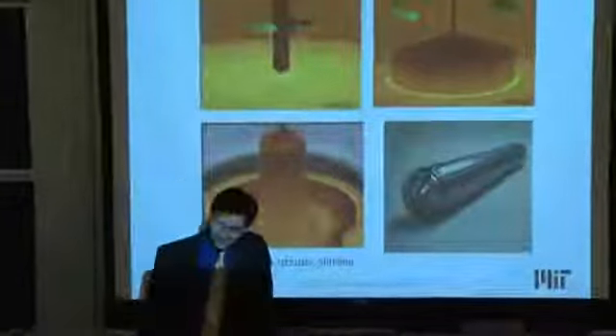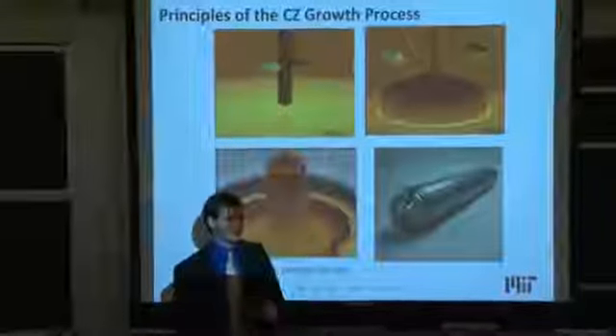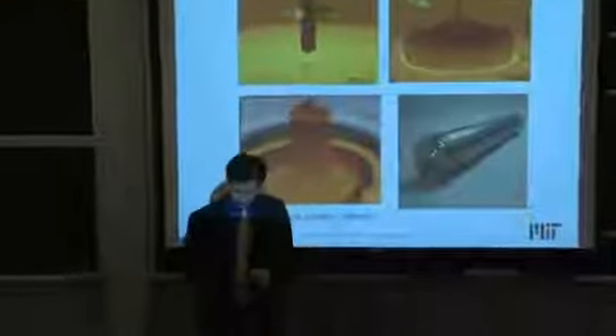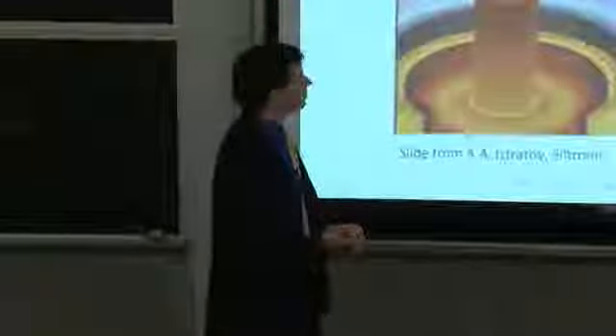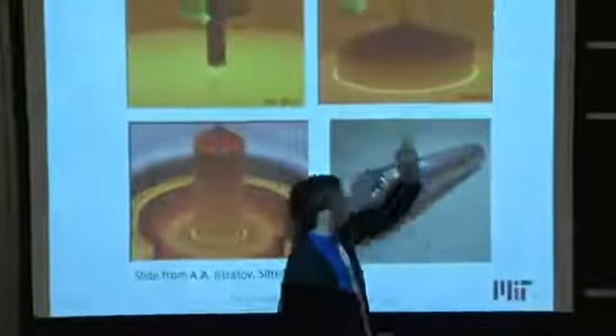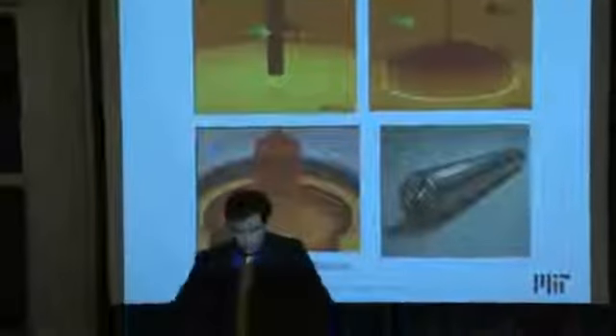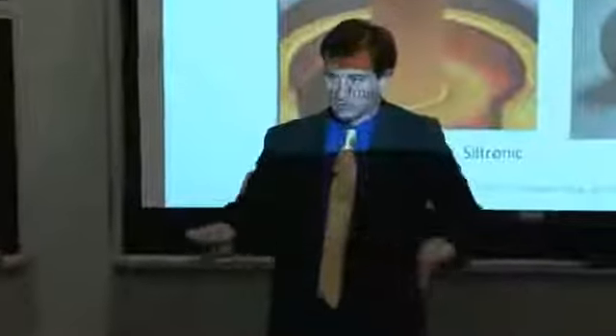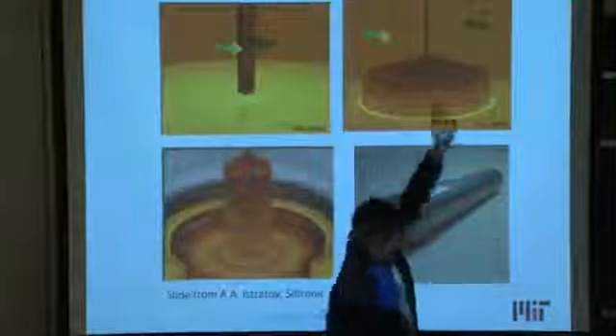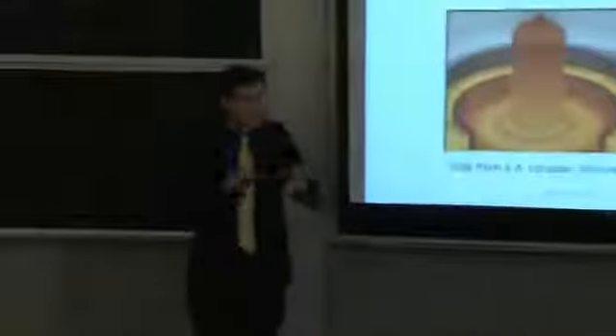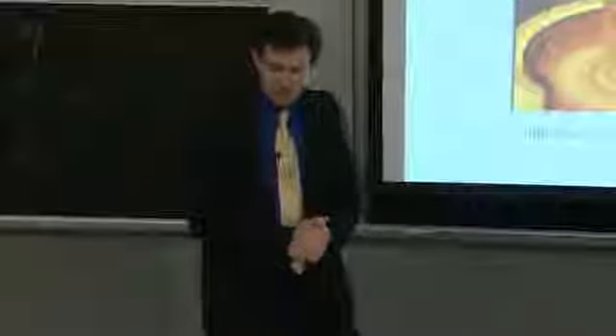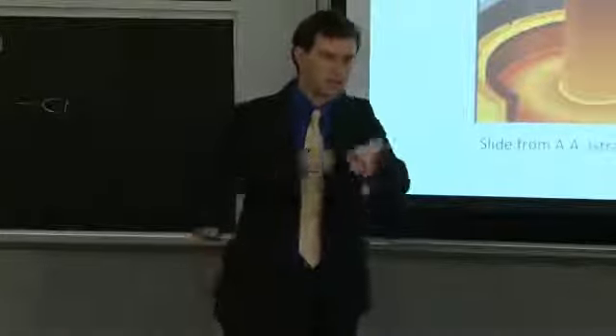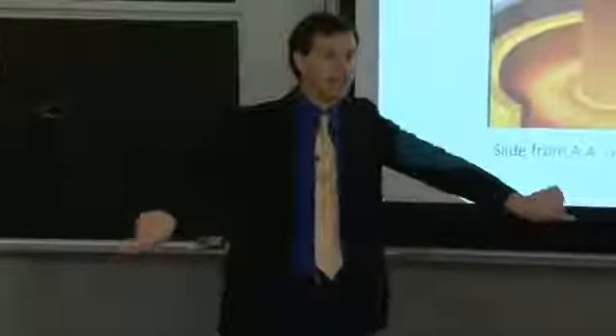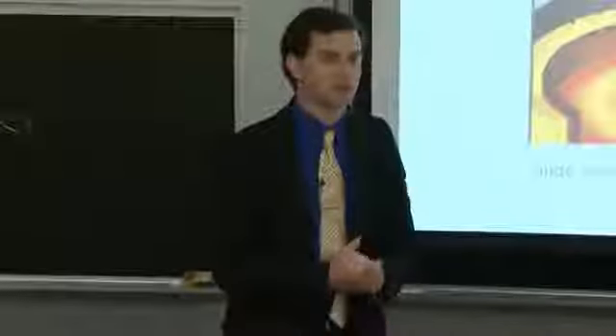You introduce that seed down into the liquid melt. Thermal stress happens, right? Because you have this shock between the solid silicon seed encountering the liquid for the first time. So dislocations form, and you have to pull the seed out in such a way that you slowly rotate and make this shoulder. The shoulder has to be as quick as possible because you don't want to waste material. Everything inside the shoulder right here gets thrown away. So that little piece of material right there gets tossed out. So you want to make the shoulder as narrow and as quick as possible so you can utilize the majority of your ingot. But at the same time, you have to make it thick enough so that the dislocations can move all the way and propagate to the outside and terminate in the shoulder before propagating into the crystal. And so that's just one example of the technology that goes into growing these.